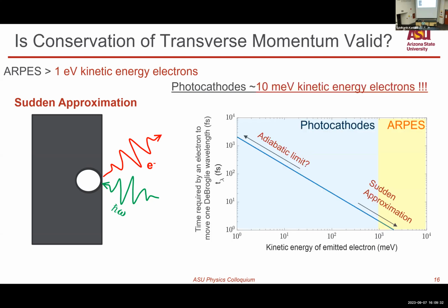However, ARPES always uses electrons with energy greater than an electron volt or so. The electrons that we are interested in have 10 milli-electron volt scale energies, very, very small. They're going out extremely slowly. And if you consider the time required by an electron to move 1 de Broglie wavelength and plot it versus the kinetic energy, if you have an eV electron kinetic energy or greater, this time is less than a femtosecond. And in a femtosecond, things usually don't interact with electrons that easily. However, if you look at the same thing for a 10 milli-electron volt electron, you'll see it's 100 femtoseconds that it takes to move 1 de Broglie wavelength.